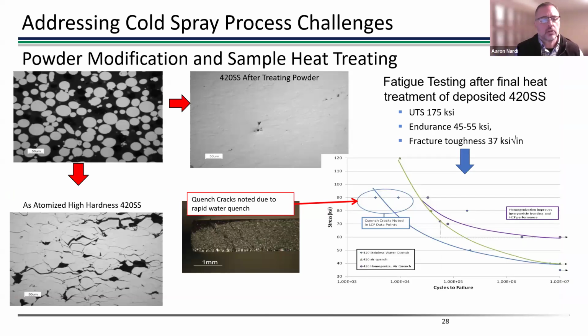There's a lot that's been done over the years with powder processing. You'll probably hear a lot more from Solvis on that in CSAT. We're doing a lot of work with a variety of different powders, looking at processing of those materials in different ways to get better quality. That's sizing, that's heat treating, that's a variety of other things that can be done to those powders. And then when you do it right and you start to look at additive manufacturing, you can get some really fantastic properties. This is just showing some fatigue properties of 420 stainless steel, but you'll actually see some more properties from materials in my CSAT presentation with Inconels and other aluminums and so forth.